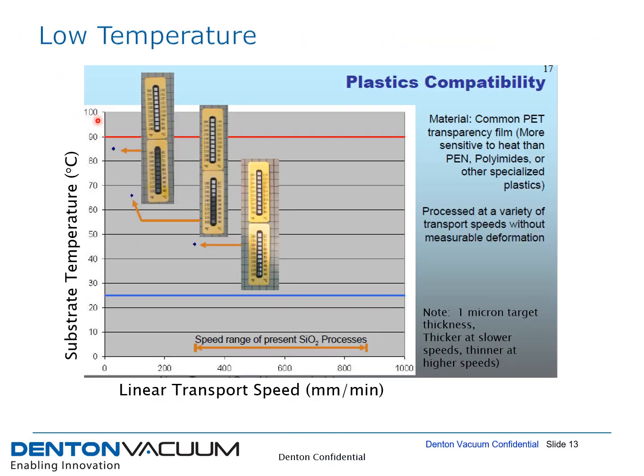So what we have measured here is the substrate temperature as a function of the linear transport speed of the substrate for a given ion energy and ion current density. And what we see here is, first of all, temperatures below 100 degrees centigrade, which means it's very suitable for plastics and flexible substrates. And moreover, when you increase the speed of the substrate, the temperatures can be further reduced. So that's a very important thing when it comes to coating flexible substrates.